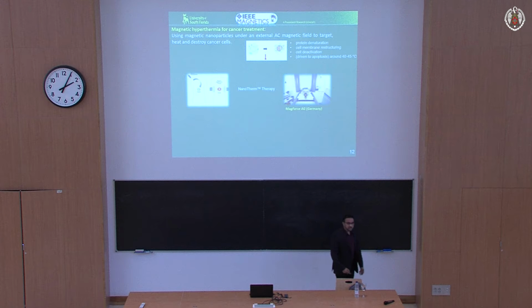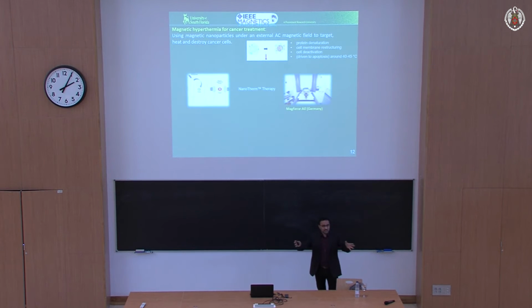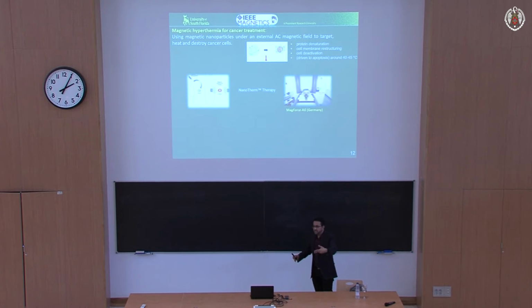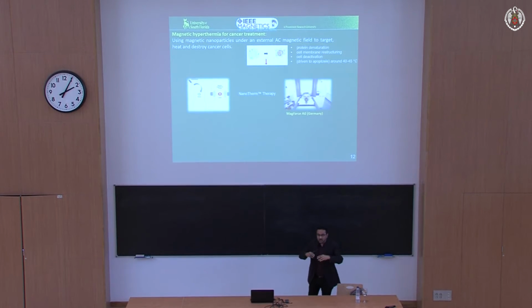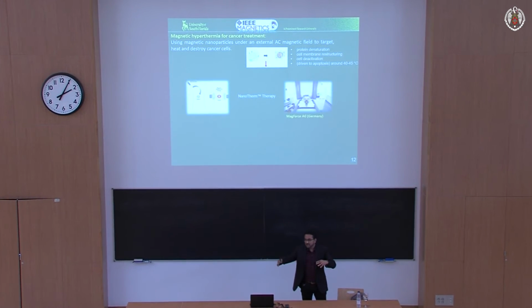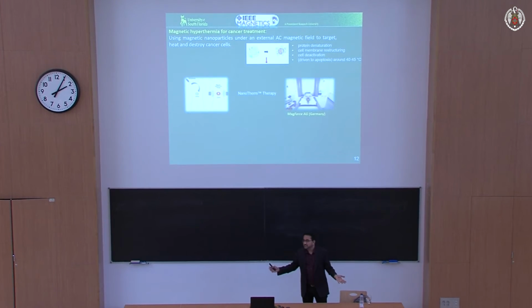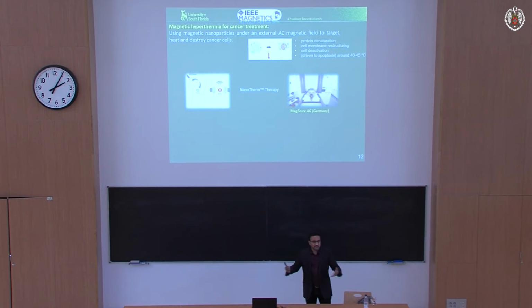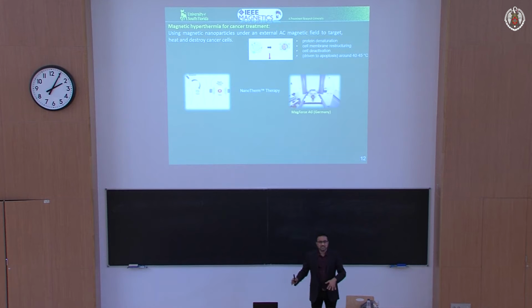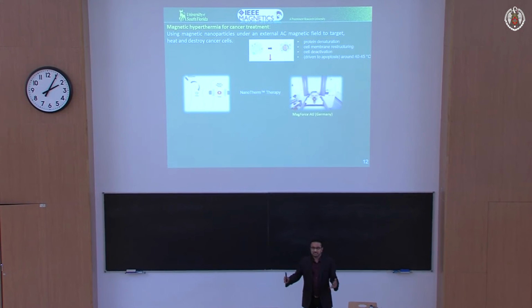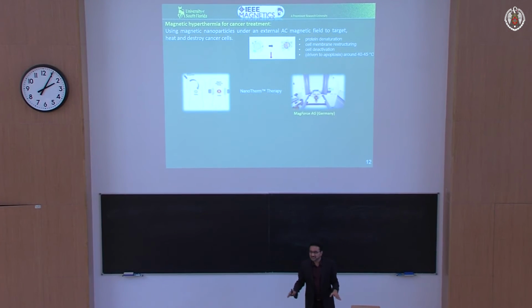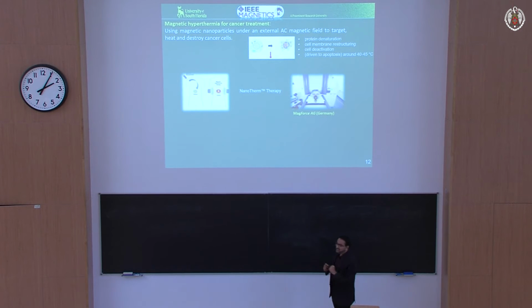Okay, so how are we going to do this? We are going to heat up, and it turns out that all you need to do is heat up the local temperature just by a few degrees Celsius. The therapeutic window is 40 to 45 degrees Celsius, so it's just a few degrees above the body temperature. Sustain this heating for some time, 30 minutes to an hour, and you kill the cancer cells. Cancer cells do not like heat. They do not like Florida in summer. Okay, so basically that's how we are going to do it.